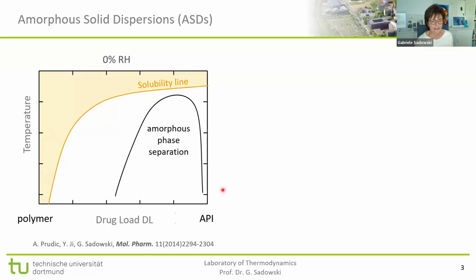melting point. So we are down somewhere here, where the solubility region is smallest. And unfortunately, this is not enough. The drug load is given by the therapeutic dose, and usually this is either here or there. So that means these systems are usually not stable in the sense that they will change over time, either by crystallizing the API or by demixing in a tablet, or both, which is both unwanted. And for that, it's important to know, of course, where the solubility line and the LLE line is. This is in a dry system. So we have no water in the system nowhere. So this is for the dry system, but for the storage, it's of course usually storage at room conditions.